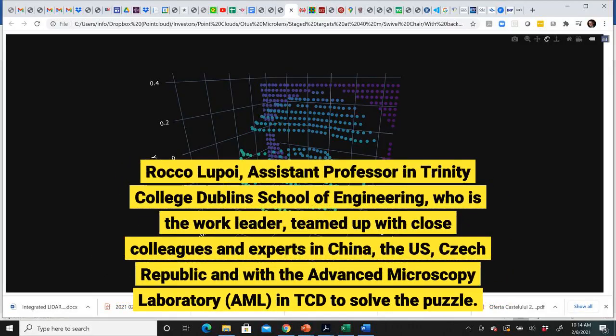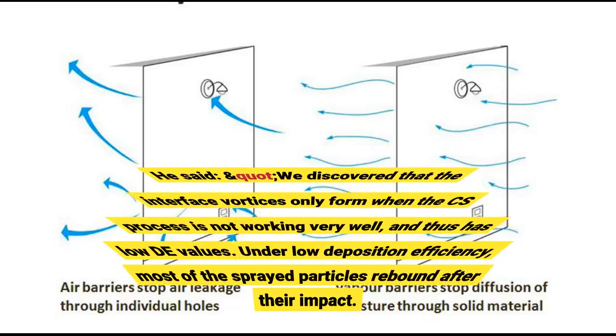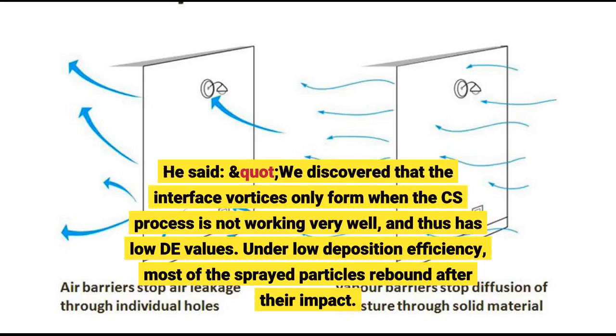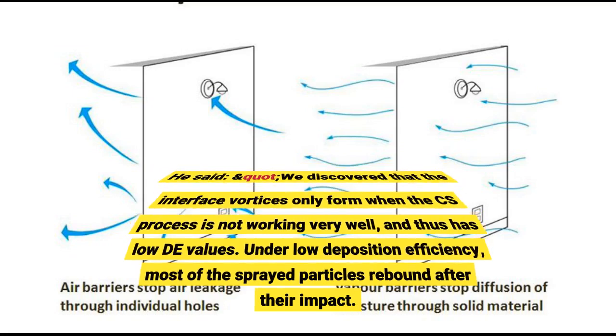Rocco Lupoi, assistant professor in Trinity College Dublin School of Engineering, who is the work leader, teamed up with close colleagues and experts in China, the US, Czech Republic and with the Advanced Microscopy Laboratory (AML) in TCD to solve the puzzle. He said, "We discovered that the interface vortices only form when the CS process is not working very well, and thus has low DE values. Under low deposition efficiency, most of the sprayed particles rebound after their impact. By causing severe plastic deformation of the first layer coating and substrate, this results in a hammer effect, which leads to the formation of the vortices.